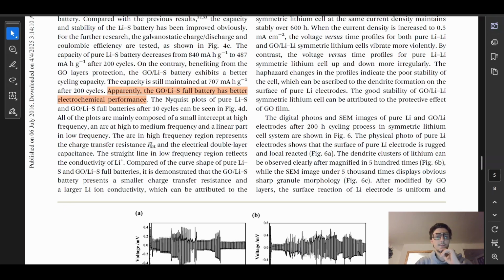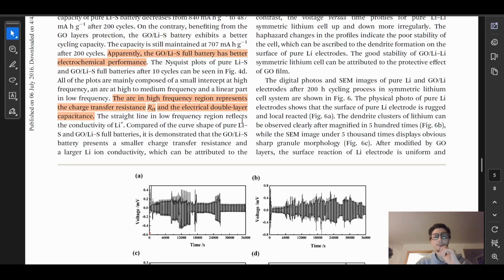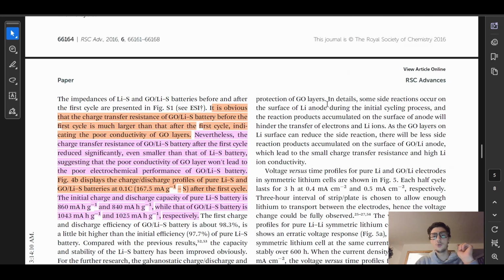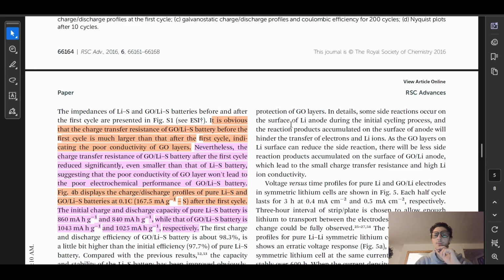Okay, so the arc in the high frequency region represents the charge transfer resistance and the electrical double layer capacitance. Cool, highlight this. The straight line in the low frequency region reflects the conductivity of lithium ions. Compared to the curve shape of the pure lithium sulfur and the graphene oxide lithium sulfur batteries, it is demonstrated that the graphene oxide lithium sulfur battery presents a smaller charge transfer resistance and a larger lithium ion conductivity. I'm going to highlight this as well, this is important. All of this can be attributed to the protection of the GO layers.